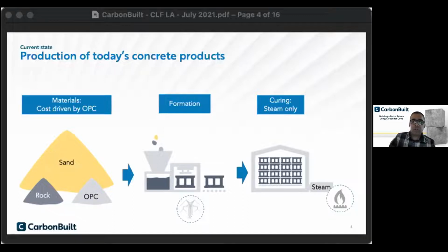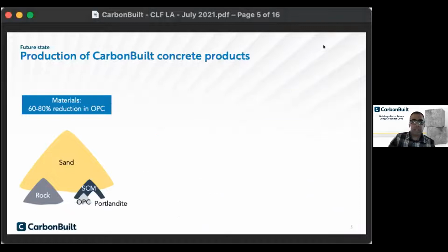So when we switch over to our process, that's again happening at the front and the back end of the process. The first thing we do is change those materials. So I mentioned the 60 to 80% reduction in the amount of Portland cement that's used. We substitute for that in two ways. The first thing we're doing is adding a new material called Portlandite, otherwise known as hydrated lime or calcium hydroxide. This is a commodity chemical today. It traditionally is made from limestone, in similar ways to Portland cement in that it's heated in a kiln. It's got a slightly better carbon footprint, all other things being equal, because the temperatures it's produced at are lower.